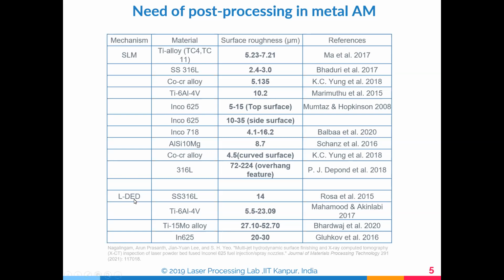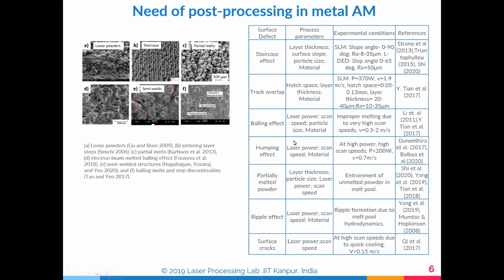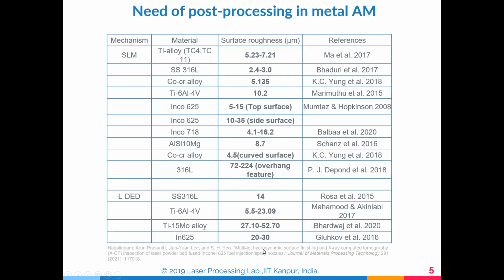When we talk about direct energy deposition, you again have stainless steel, Ti6Al4V, Ti alloys, and Inconel 625 alloys. So these are some of the materials available. And predominantly when we look at polishing, we take this property and play around with it to try to reduce the roughness from 10 microns to 1 micron or less than 1 micron. So that is the major challenge we are looking at.